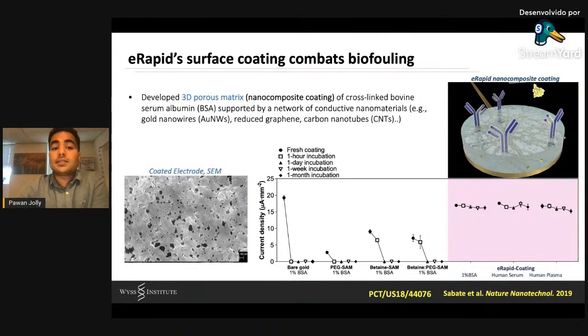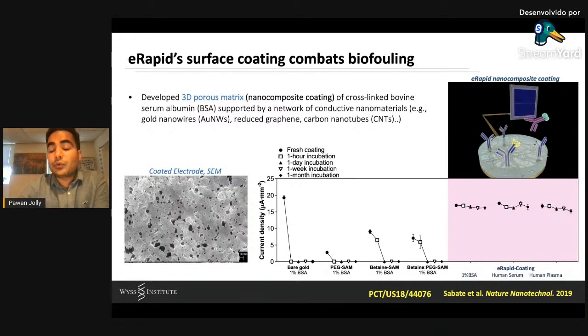What we have developed is a 3D porous matrix, a nanocomposite coating, which is a cross-linked denatured bovine serum albumin, which is intercalated with nanoparticles, either gold nanowire, reduced graphene, or carbon nanotubes based on the application via a cross-linker. And with this specific recipe, one of the key features you have to look at here is when we coat these sensors with our coating, you retain more than 95% of the conductivity of the metal. And when you challenge these sensors in 1% BSA or human serum or even human plasma for over a month, you retain nearly 90% of the conductivity.